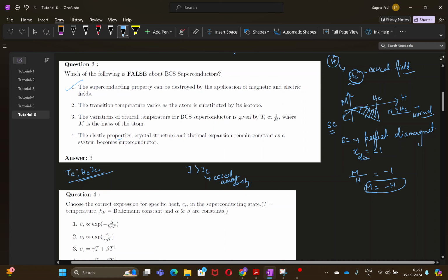When you control via the temperature and all the other parameters are absent, that means no field and no current is given, then as you increase the temperature beyond Tc, you lose superconductivity. But let's say you are much below Tc, well in the superconducting zone, and you still apply a field and keep on increasing the field value to finally exceed the critical value for the material, which is Hc, then you will lose superconductivity because you will be breaking the Cooper pair.